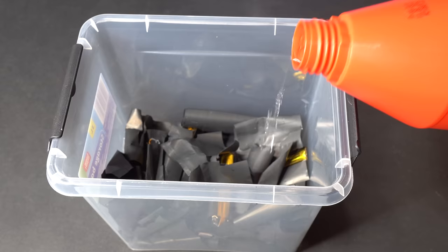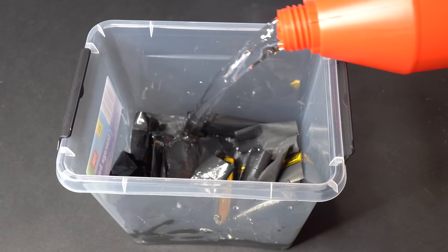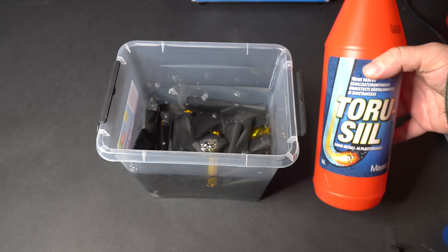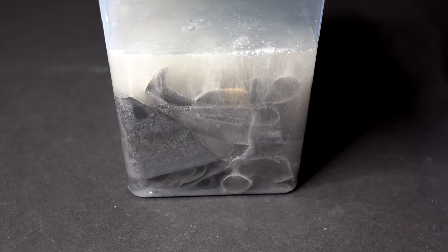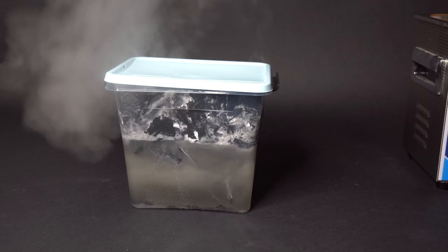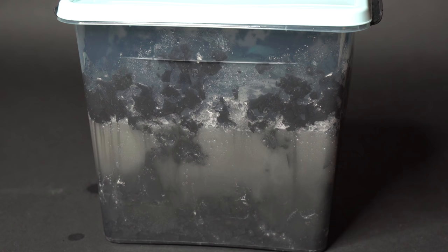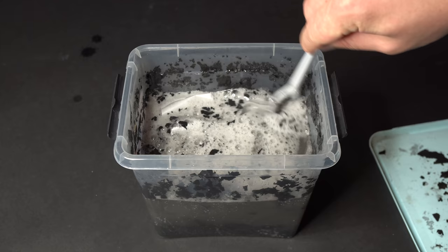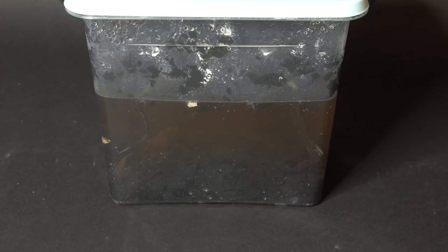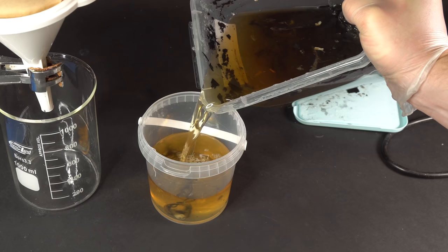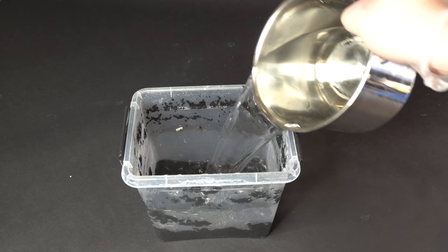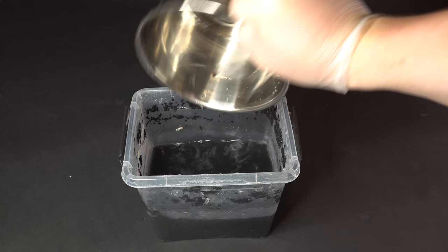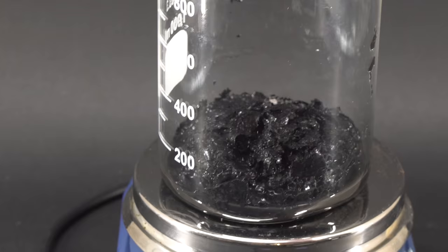After drying the cathodes, first we need to separate that very black mix of oxide from the aluminum base, which is why I am filling the container with a regular drain cleaner, which is a 12% sodium hydroxide solution. The aluminum foil starts dissolving in sodium hydroxide, whereas the oxide mix doesn't react well with this chemical. That is why this black mass eventually sinks to the bottom. The reaction runs quite quickly. After that, I leave this mixture for another hour in order to dissolve the leftover foil in the alkali. In order to separate all of this, I am just pouring out the top layer of the liquid, and after that I am rinsing it in water. Fortunately, the obtained oxides are heavier than water and they easily sink to the bottom.